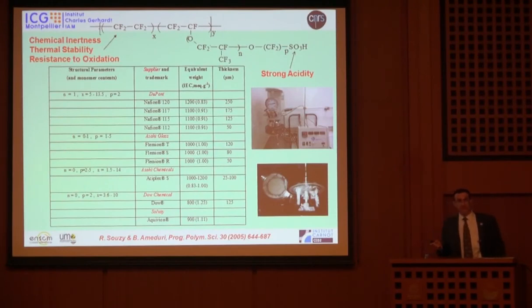So the design is very interesting because you have a backbone which is perfluorinated, which confers the chemical inertness, the thermal stability, the resistance to oxidation. Just remember what I mentioned as properties at the beginning of a fluorinated material. And on the side group, you have some sulfonic acid group, which is adjacent to a CF2 electron-withdrawing group, making the acidity much higher. So the design already of this polymer is very interesting.